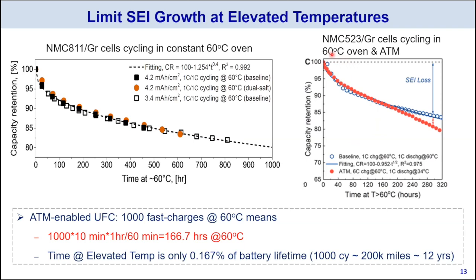Similarly, our early data using NMC523 graphite cells does the same thing. The blue symbols are basic constant oven testing at 60 degrees Celsius, and the red ones are ATM operation, which does the 6C charging at 60 degrees Celsius and 1C discharge at much lower temperature. But still, at the very beginning, you basically see those two data sets coincide with each other. And it's all about time. So time will decide the capacity retention.